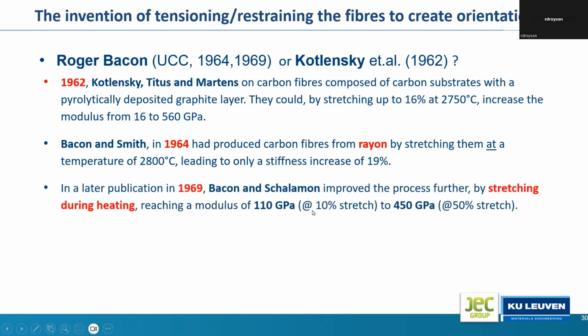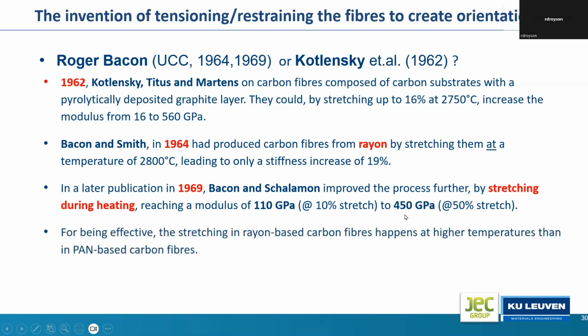And then 5 years later, they published and filed patents where they said, you have to stretch during the heating, meaning during the oxidation phase, and then you can increase the stiffness up to 450 gigapascal. So for being effective, the stretching of rayon-based carbon fibers must happen, and they still were working on rayon-based fibers, so they needed somewhat higher temperatures to do that than for PAN fibers, but that's a detail.